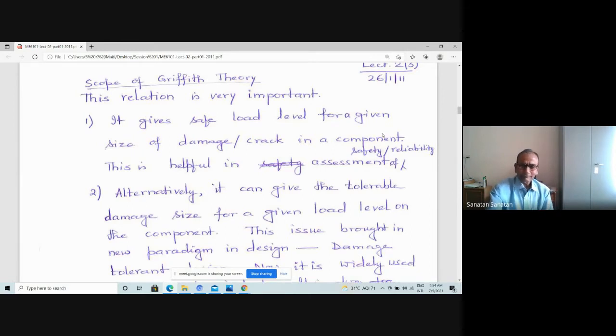Please note that it gives you the critical load capacity once you know the geometry of the structure and the crack size in it. Alternatively, if you have a structure and you have loading, then you can ask the question, how much crack or damage can be tolerated? That is what damage tolerant design is. How much damage or defect can be tolerated in a given structure with its geometry and the loading.